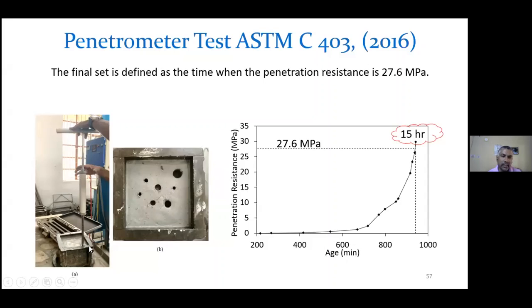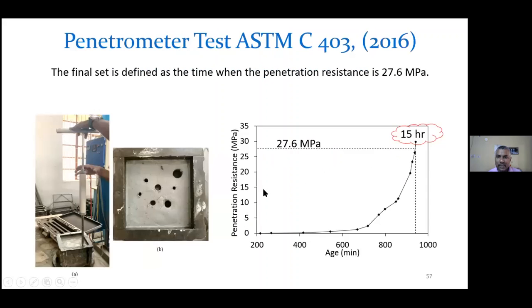So it is like penetrating a rod and finding out the resistance. Initially the resistance will be low, and after a certain time, when the resistance crosses this 27.6 megapascal, we consider it final setting. So this plot is a penetration resistance versus age plot. You can see that 27.6 megapascal is coming at almost 15 hours. So this 15 hours is, because it is also approximate, right? So this is one of the examples where we have tried to use this method.